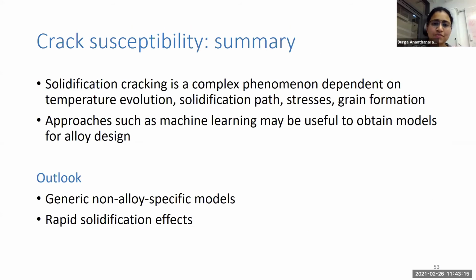But the conclusion from this part is that cracking itself is a very complex phenomenon that depends on so many different factors. And if we want really effective models for alloy design, which are fast and fairly accurate, then approaches such as machine learning may be really useful here. Looking forward, it would be useful to have more generic, non-alloy-specific modeling approaches for predicting crack susceptibility. And of course, the effect of rapid solidification should be studied more in this regard.